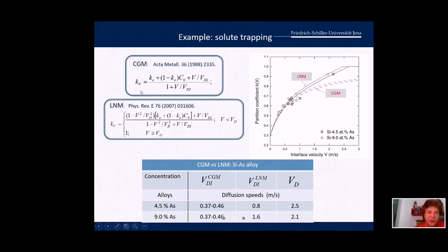The chemical segregation coefficient is defined by the ratio of concentration in solid and concentration in liquid. Normally, for the standard type of phase diagrams, we have the equilibrium solute chemical segregation coefficient K_E smaller than 1, because the solid accumulates atoms in a content smaller than the liquid.